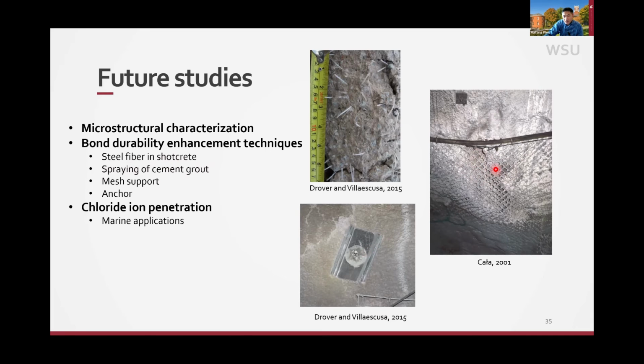So mesh can somehow support or even collect any debris from the shotcrete if it's falling apart. Or the anchor method, where you are physically anchoring the shotcrete to the concrete substrate. Another concern, especially on the west side, is the seawater, which has a lot of chloride, and how would the chloride ion affect the bond durability? That'll be another concern. We recommend more studies.